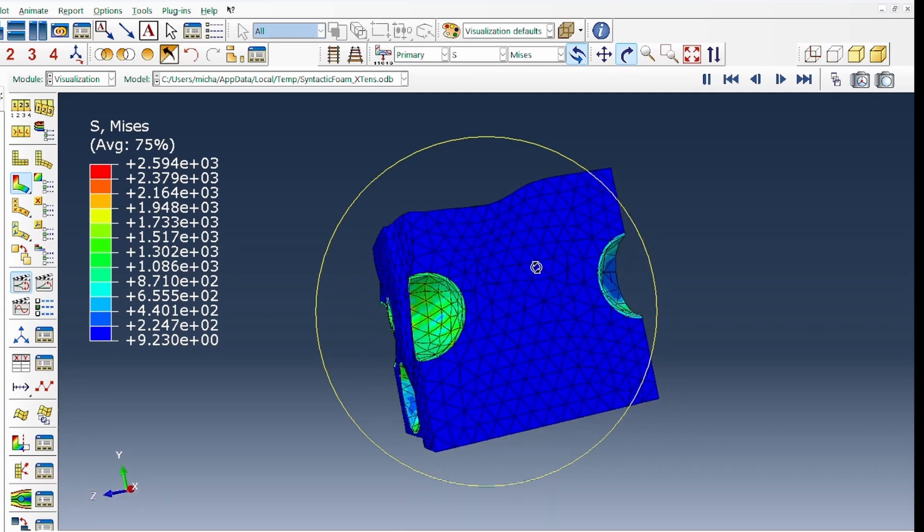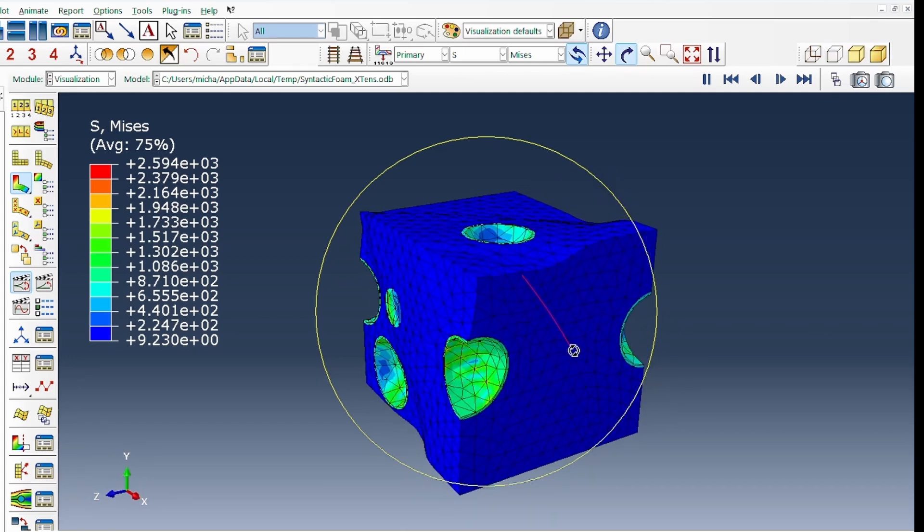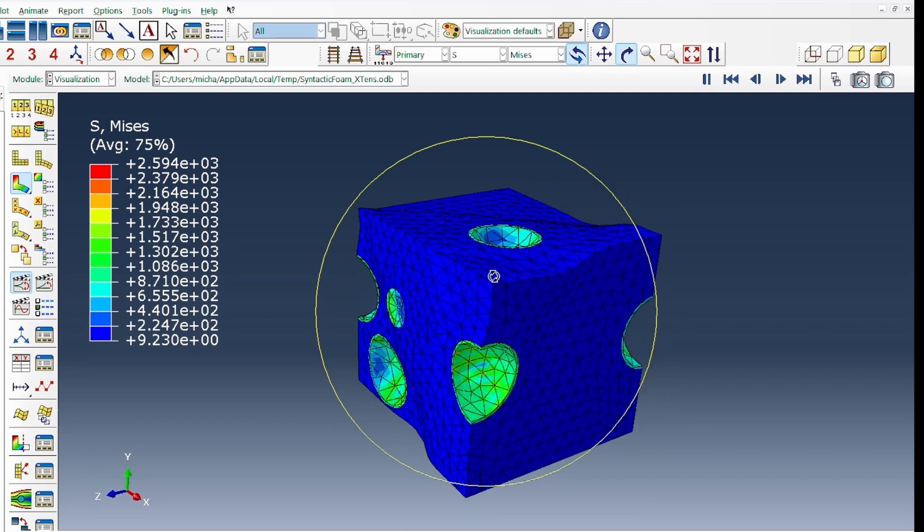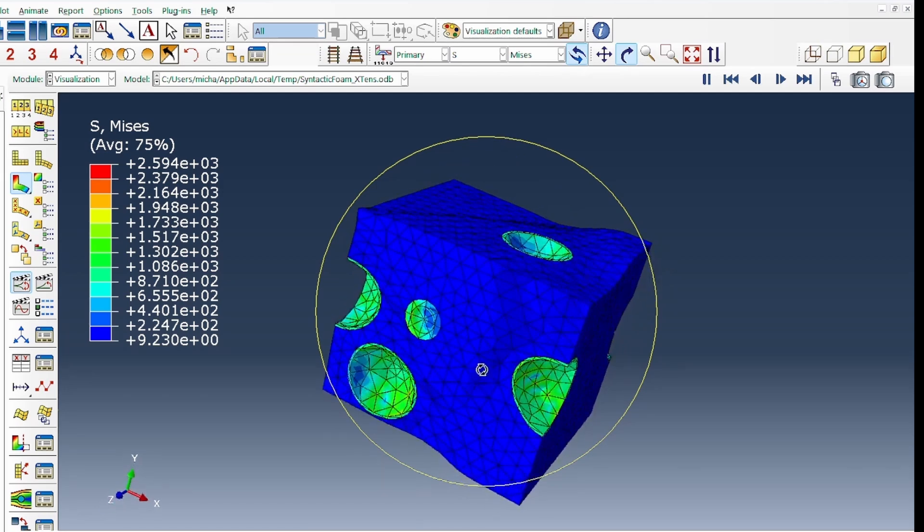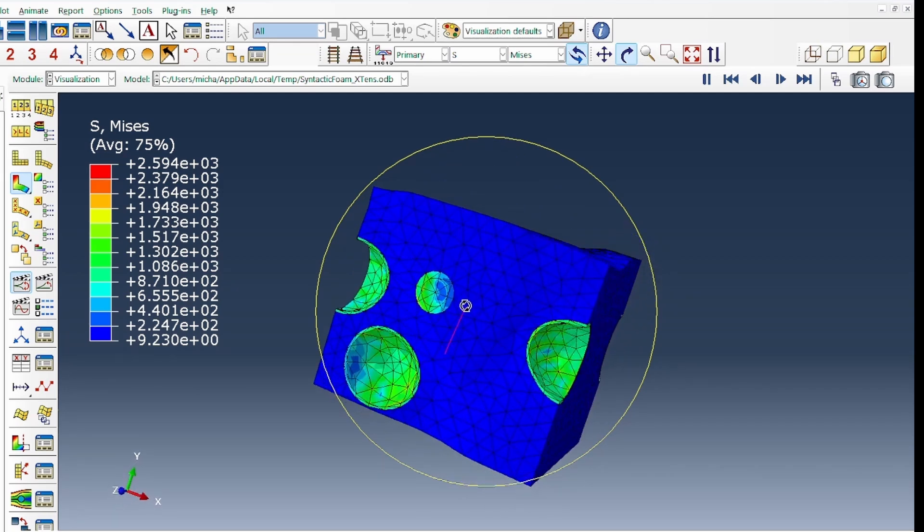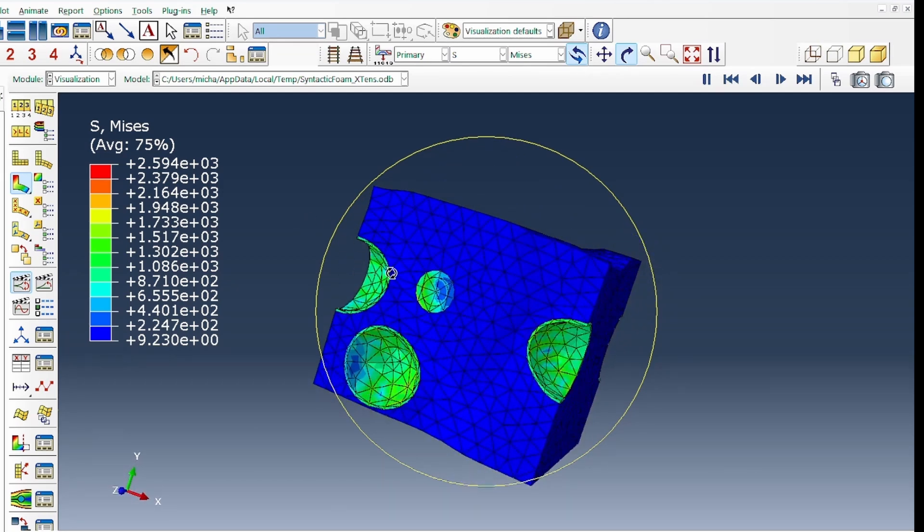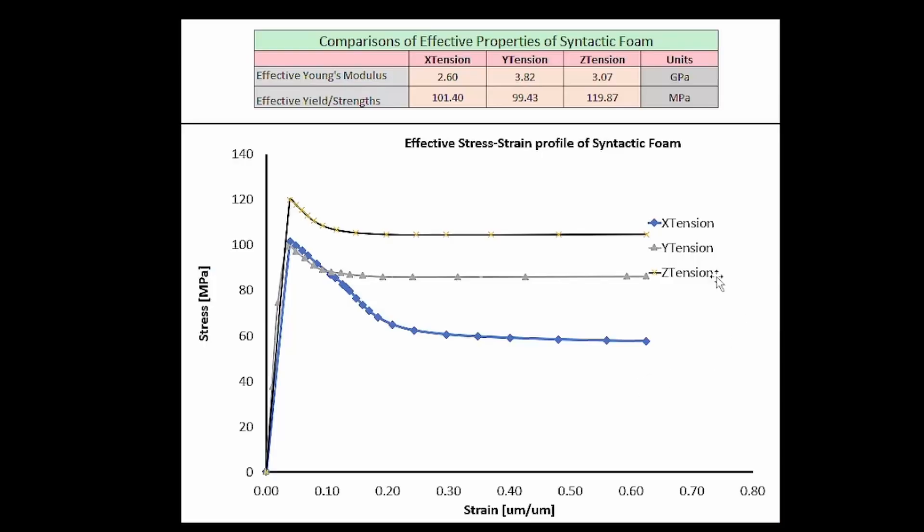The main reason for that is the nature of the different cross-sectional areas. The cross-sectional area here is different from here. In the Y direction, there's only this region that is cut out. In the Z direction, there's a lot of missing spaces, so the area will be much smaller. These are the issues we find here, and it gives us very interesting results. But this is why you need to really do some RVE sizing effect to see whether this result is actually representative.